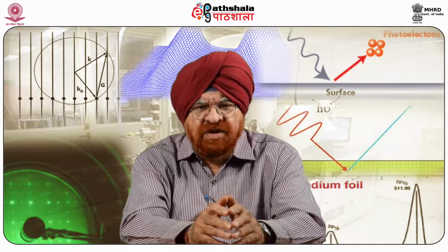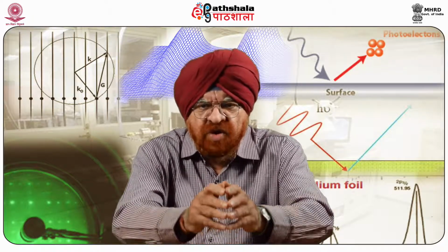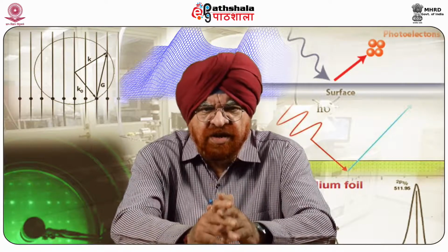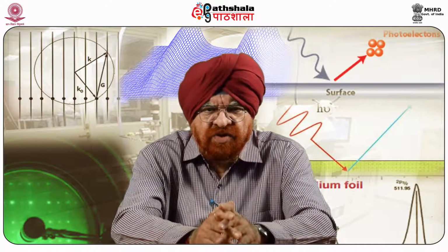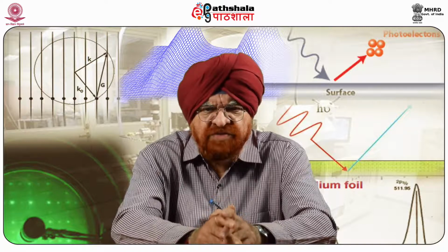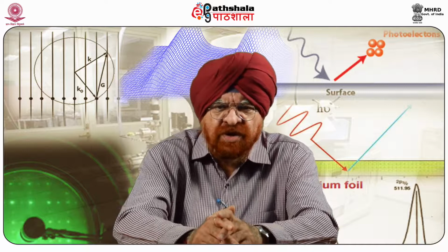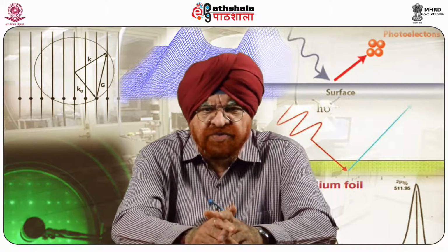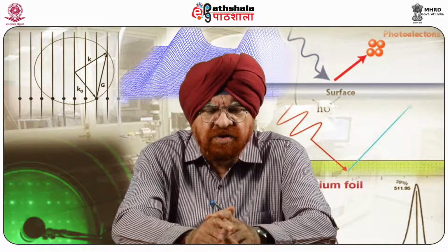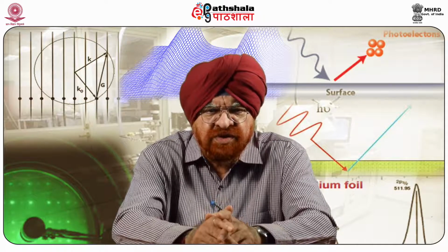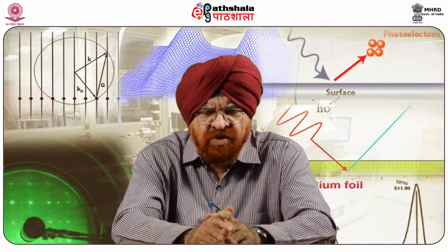For the structural analysis of atomic positions in surface unit cells, LEED I-V analysis has been developed with an accuracy of less than a few hundredths of an angstrom. Furthermore, for determination of complex surface structures, this has been automated.